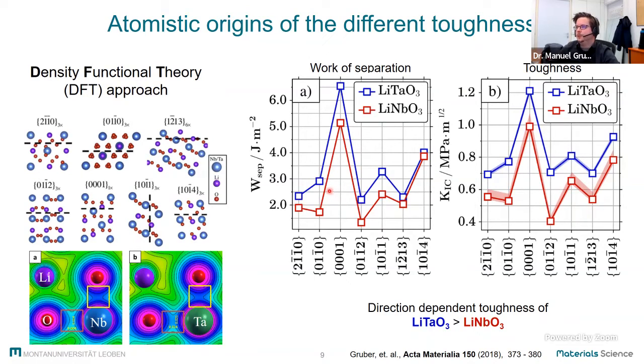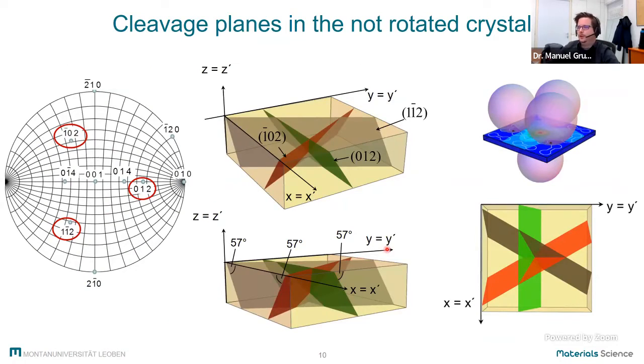What we can see here is that we have a higher toughness for each of the planes for lithium tantalate compared to lithium niobate. And secondly, that the most critical cleavage plane is this 012 family of planes along which we would expect the fracture to occur. If we would have non-rotated single crystals, the cleavage planes would be aligned somehow like this in our sample. So with an angle of 57 degrees to the surface, we can see here the nice 120 degree symmetry as expected for these unit cells I showed you before.